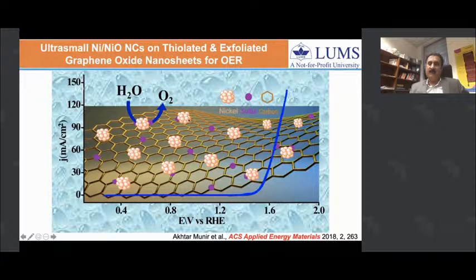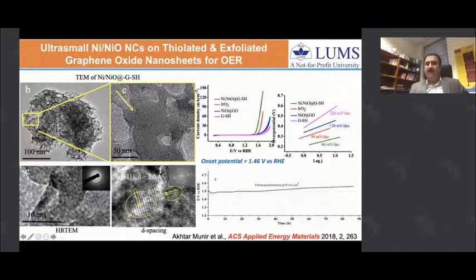These nanoclusters were again smaller than 2 nanometers, and they were really quite active to oxidize water to produce oxygen. Here the onset potential is 1.46 volts, which is really decent, and they have a quite low Tafel slope as well. More importantly, they were really stable for at least 3 days, maintaining their stability and activity under continuous CV.